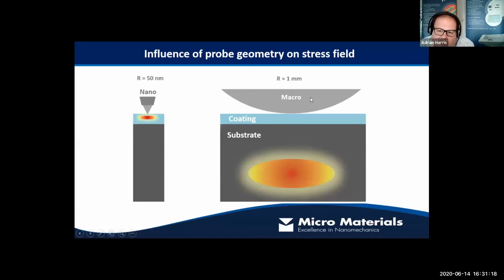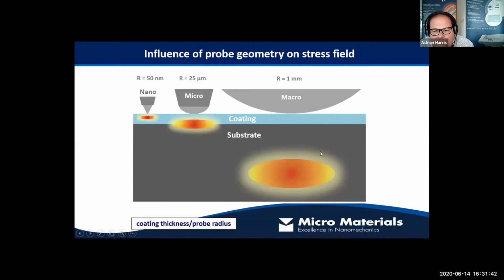Now, there are some existing macro scale impact techniques out there, but they tend to use a very big probe, say, something like a radius of 1 millimeter. And there, the problem is all of our stress maximum point is right down deep in the substrate. It's too deep, so we've gone to the other end of the scale here. So we have limited sensitivity to what's happening in the coating.